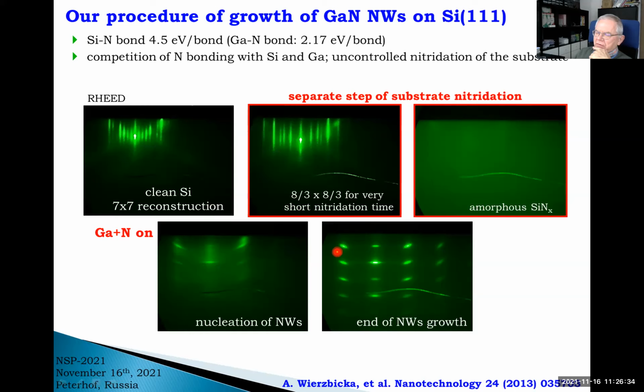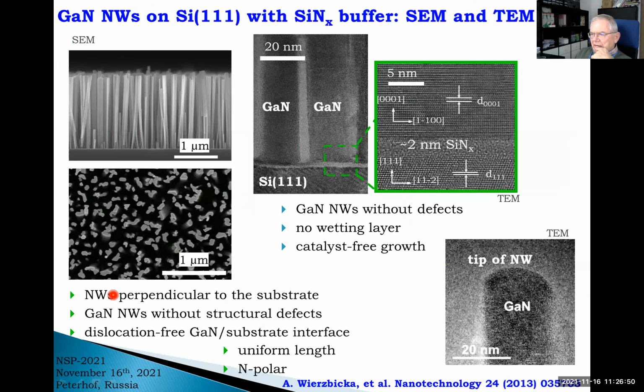So instead of leaving things as they are, we introduce an additional step, which we use before the real growth. We expose our deoxidized substrate to nitrogen flux just to create a silicon nitride film on top of the surface, and only then do we start growth of nanowires. And these are the results of such a procedure.